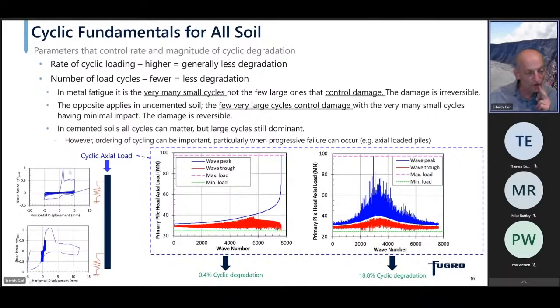But the difference here is at the top of this pile with progressive failure, we actually load it to failure early on, because this pile is being worked due to its compressibility, whereas the bottom of the pile is doing very little. So we damage the top of the pile. And what we actually find then is the ordering of the cycles makes a big difference. So here, for example, on the right-hand side, we have a storm which has a series of wave peaks, which is the blue lines in the actual storm order, and then the reds is the wave troughs. There are like 7,000-8,000 waves there applied in the actual storm order. When we apply this to our model, we get almost 19% reduction in strength due to cyclic degradation. But if I take that same storm and just order the waves from smallest to largest, we only get 0.4% cyclic degradation. And the reason comes back to this progressive failure.